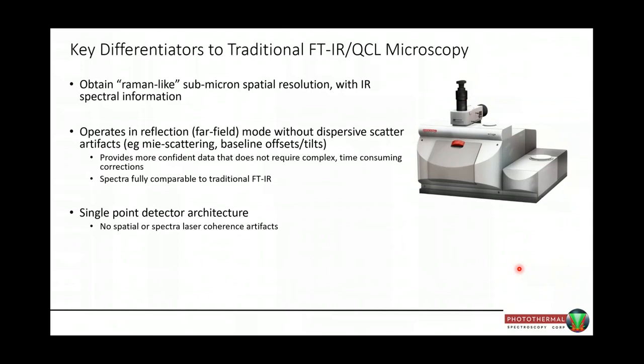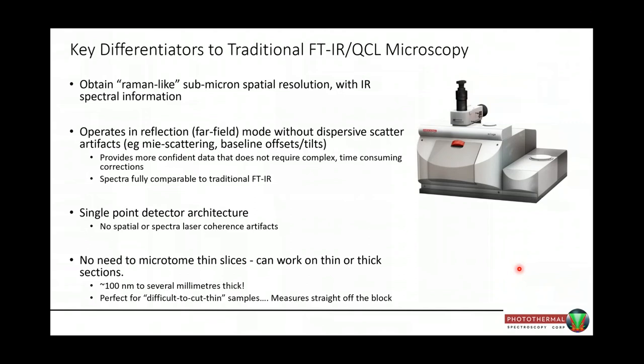There's a single-point detector architecture with no spatial or spectral laser coherence artifacts, and there's no need to microtome thin sections. You can work on thick sections from 100 nanometers thick up to several millimeters thick, so it's nice for those difficult-to-cut samples. You can measure right off a block cut of a multi-layer film, and that's how the samples that Isao will be talking about later were prepared.